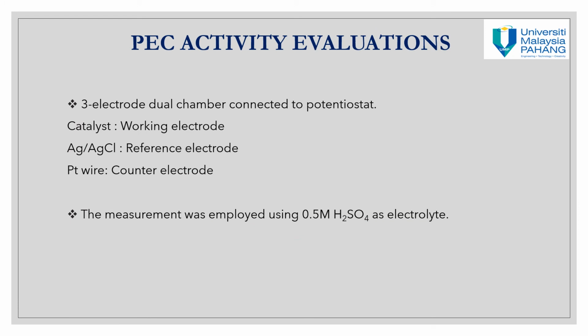Next, the photoelectrochemical PEC activity was conducted to study the hydrogen evolution reactions. In the present work, a 3-electrode dual chamber was used and connected to the potentiostat. The catalyst represents the working electrode, Ag/AgCl represents the reference electrode, and the Pt wire represents the counter electrode. In this work, 0.5 molar sulfuric acid was used as the electrolyte.